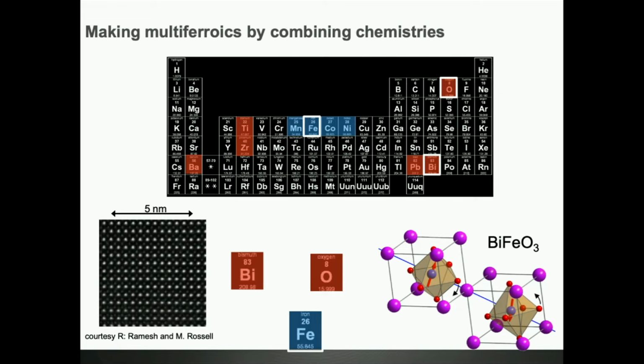So here's a high-resolution transmission electron micrograph from Marta Rossell, who's now at EMPA in Zurich, of a film grown by the group of Ramesh at UC Berkeley. And you can see the white dots here are the bismuth atoms. Maybe you can just about see the iron atoms also. And I'm showing you this to show you that this is a really perfect thin film. And so the state of thin film growth had evolved to the stage where we were able to produce these materials and really measure that they were multiferroic. So that was our first pathway to making multiferroic materials, just combining the chemistry that gives good magnetism with the chemistry that gives good ferroelectricity.